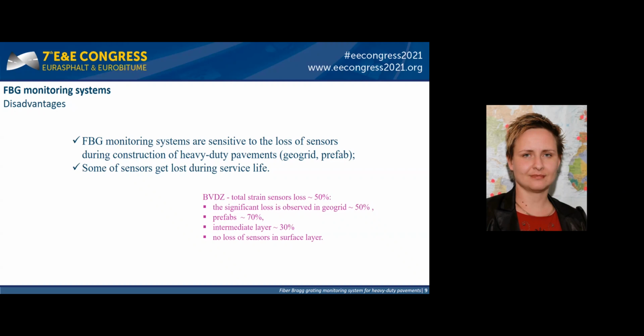Here, for example, you may see the total sensor loss during installation in 2019. We lost mostly 50% of sensors, and they were mostly related to the GeoGrid and prefabs. And there were no lost sensors, for example, in the surface layer. Also, during service life, you might lose several sensors.